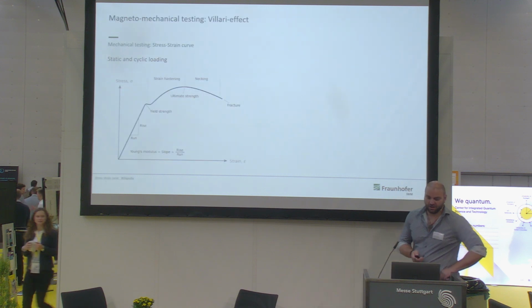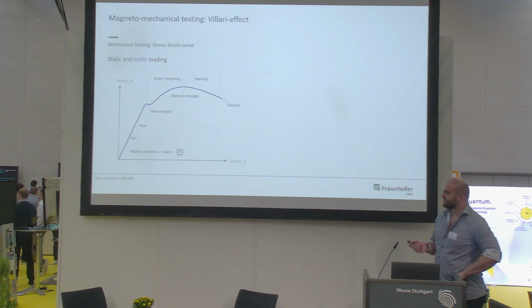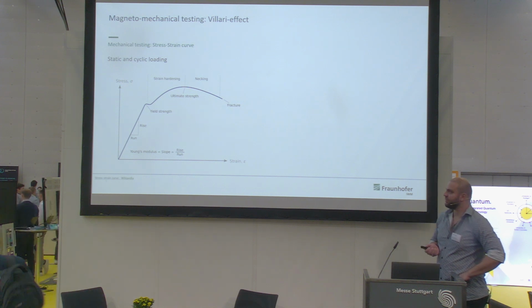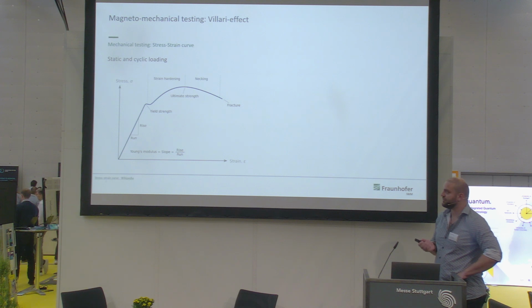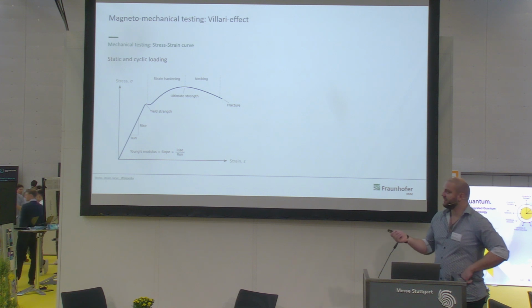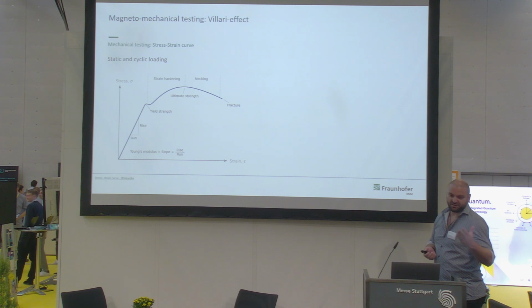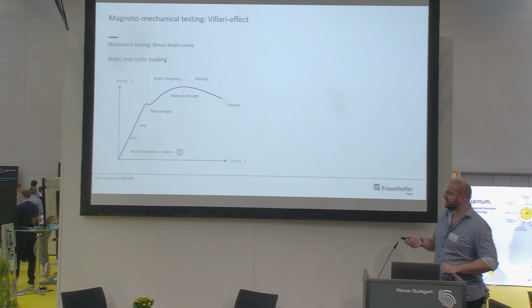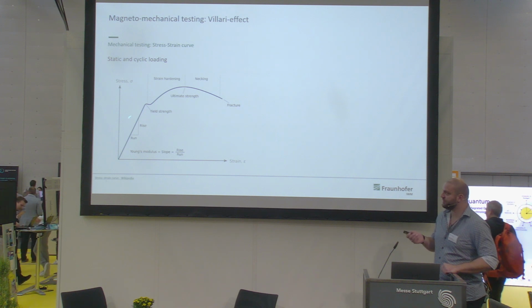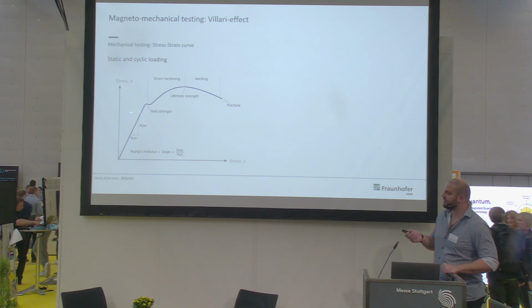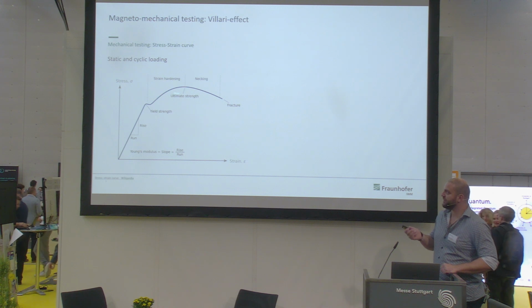So let me start with how we see any signal. I will start with mechanical testing. Typically, in a mechanical testing procedure, we have some sort of material and we apply a strain, so we pull on it and we measure the force that is applied. We take the force and divide it by the area of the sample cross-section and we get the stress, so we have a classical stress-strain curve. This is the quasi-static tensile test, which is characteristic for technical materials. We have, of course, Hooke's law in the beginning, which gives us a Young's modulus, and we go to plastic deformation and then to fracture.